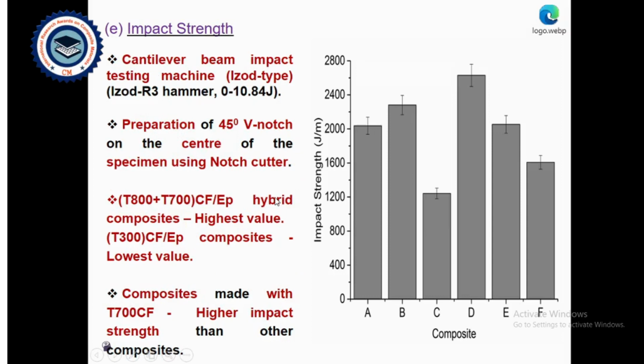Impact strength. Here the cantilever beam impact estimation, Izod type, was used, with an Izod R3 hammer and 0 to 10.84 joules. A 45-degree V notch was prepared at the center of the specimen using a notch cutter before doing the impact test. T800 and T700 carbon composites showed the highest value, whereas the T300 showed the lowest value. The composite made with T700 showed higher impact strength than other composites.